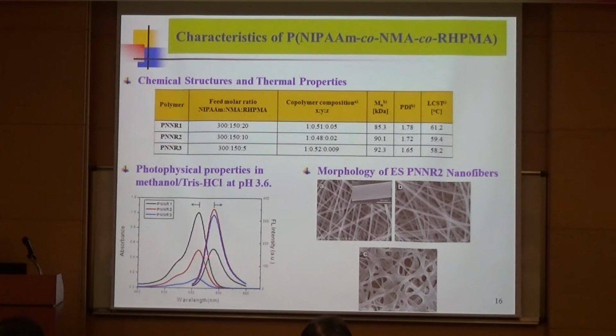From the UV and PL spectra of these 3 random polymers in aqueous solution in acidic condition, we can observe the absorbance increase with increasing rhodamine content. However, the fluorescence intensity was significantly quenched for the PNNR1 copolymer with the highest rhodamine content. This might be due to possible aggregation of the rhodamine moiety at such high composition. So we chose the PNNR2 random copolymer with moderate rhodamine content for further study of its sensing performance.